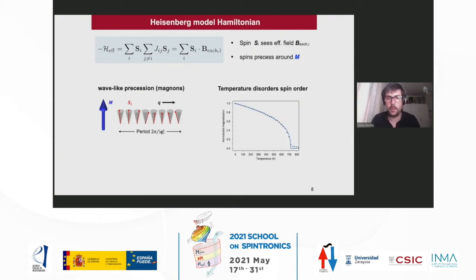And we obtain this magnetization against temperature curve, which is very well known. The magnetization decreases as a function of temperature until some critical temperature, or Curie temperature, where the magnetization is zero. So the thermal fluctuation can act against exchange interaction.